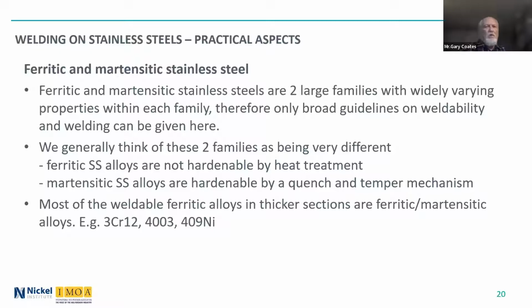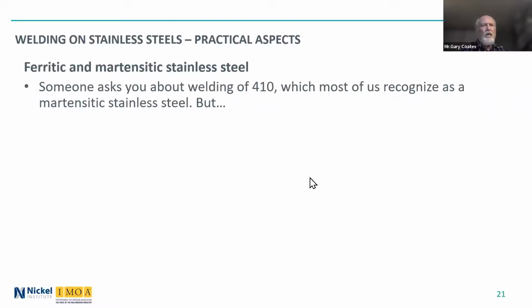But what is complicated and not really well understood is that when they call a weldable ferritic alloy, especially used in thicker sections, it's actually a duplex grade, although not the austenitic-ferritic duplex, but a ferritic-martensitic grade. You're familiar, I'm sure, with 3CR12. The Europeans call it 4003. In North America, we have a 409 nickel. They all have a slight nickel content, and they are not truly ferritic stainless steels. And I'll talk briefly about them later. And one of the most challenging issues I have is when somebody phones up and says, how do I weld 410 stainless steel?